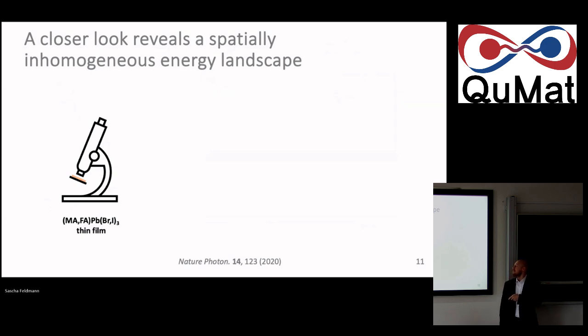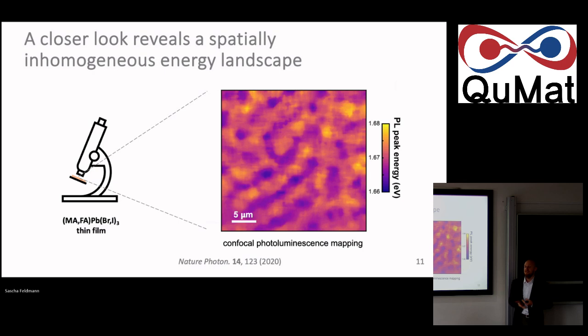Now, if we take a closer look at such a thin film after we've made it, and here I look at a methylammonium, formamidinium, bromide, iodide cocktail of ions, which works well, so a mixed halide one. And when I say closer look, I mean we literally look at it with a confocal luminescence microscope, then you might see something like this. You might see a very much not perfectly flat energy landscape. You see here the luminescence peak energy, so the color of the light that fluoresces at you, is varied by tens of milli-electron volts in domain sizes of a couple of microns or so.